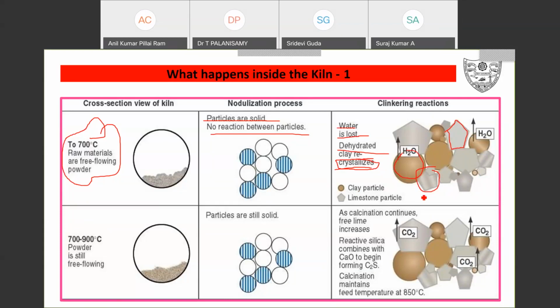This is the limestone particle. Now increase the temperature to 700 to 900 degrees centigrade. Powder is still free flowing. Particles are still solids. What is the reaction happening inside? As the calcination continues, free lime increases. Calcination is nothing but you heat the limestone, it becomes a calcination process. Due to the calcination, the free lime increases. Reactive silica combines with CaO to begin the C2S compound.